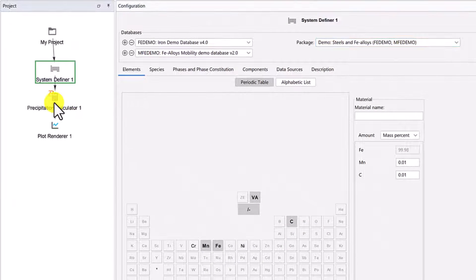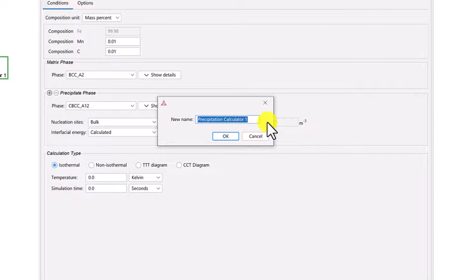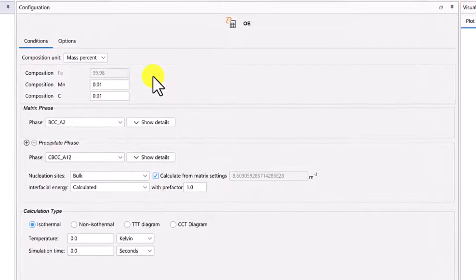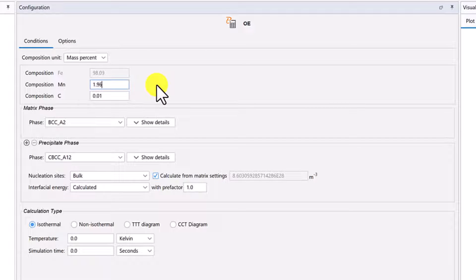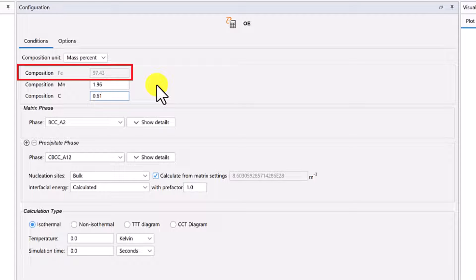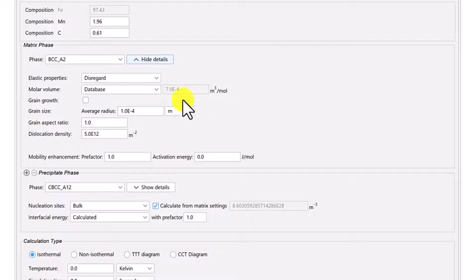Right-click on the precipitation calculator node and select Rename. This example will have three precipitation calculators, so we will rename them so that we can tell them apart. Name this node OE for Ortho Equilibrium, then click OK. From the top, we will leave the composition unit as mass percent, but we will set manganese to 1.96% and carbon to 0.61%. This automatically sets iron to 97.43%. Set the matrix phase to BCC_A2, then click Show Details.